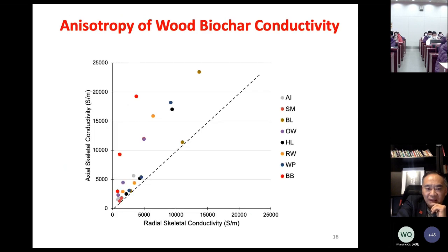Another finding is the anisotropy of wood biochar conductivity. What that means is that the conductivity of wood biochar along the axial direction is always higher than along the radial direction. Okay, so regardless of the precursor here, the reason behind that is a preferred orientation of graphite crystals in those wood biochars.